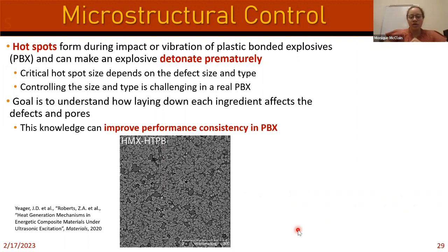When we're looking at a plastic bonded explosive, that's pretty similar to a solid composite propellant. If you think way back to those slides where we had some particles and some smaller particles in a matrix, it's similar to that, but with a higher content of particles. Essentially, there could be defects that form within a plastic bonded explosive. For example, there could be very tiny pores, or there could be a cracked crystal, or a crystal could debond from the polymer. All of those defects will change the sensitivity of that explosive.